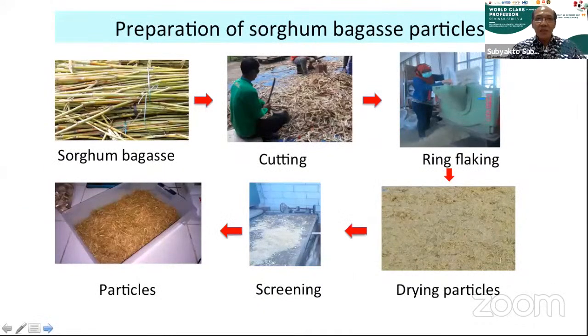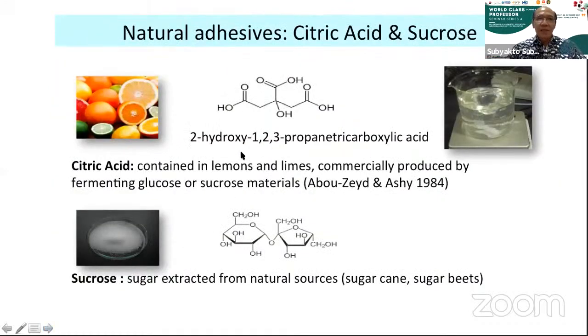And this is the preparation of the sorghum particles. So we cut, and then using a ring flaker, we got these particles. And then we use natural adhesive, citric acid and sucrose. This adhesive was developed by Prof. Umemura from Kyoto University as an alternative for the synthetic adhesive.